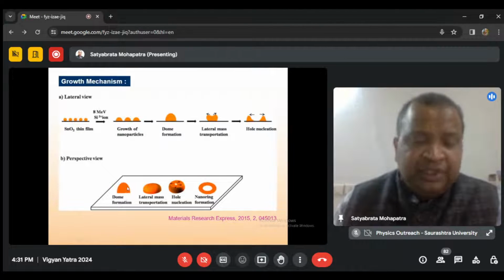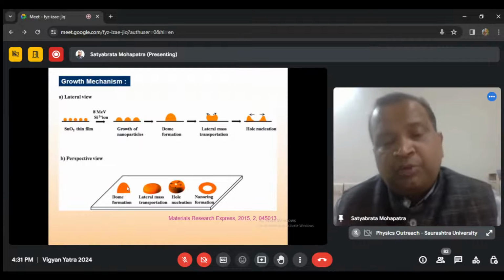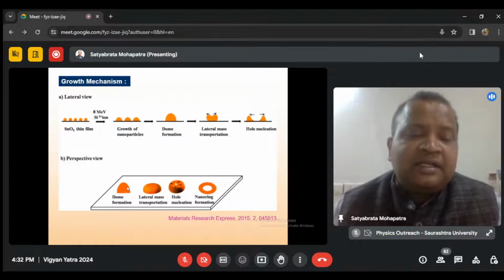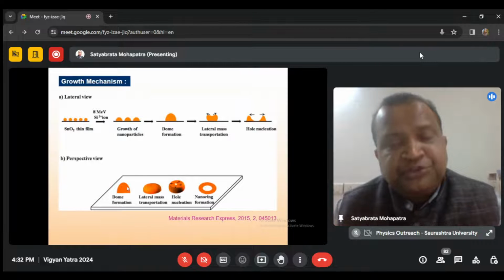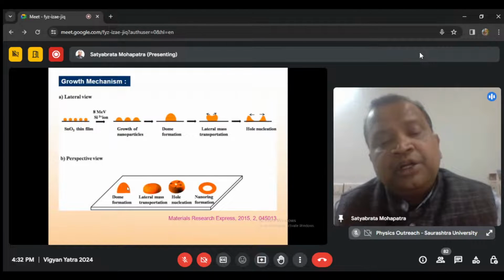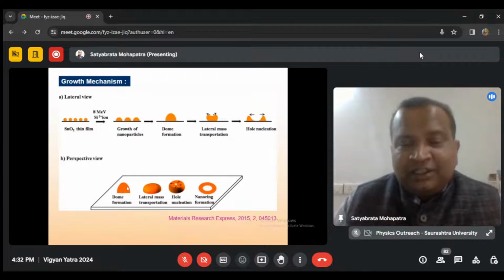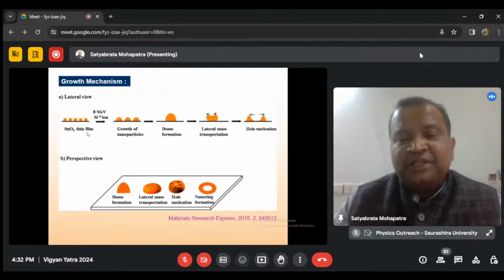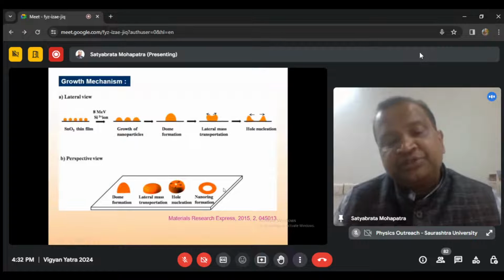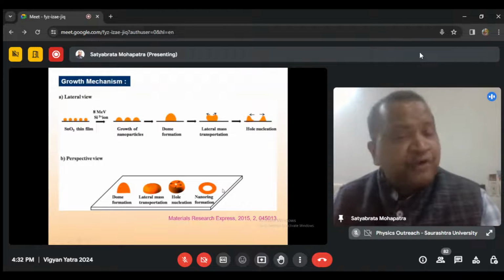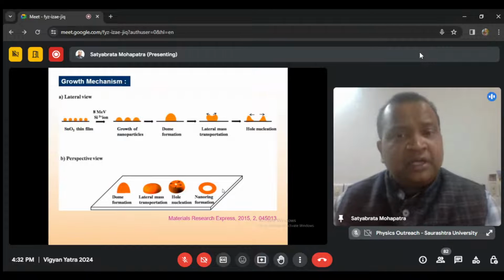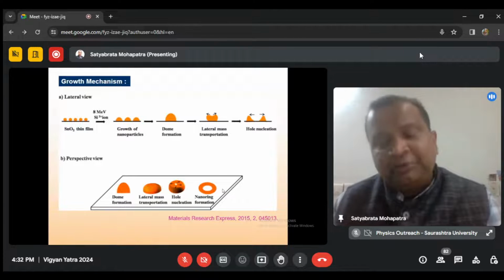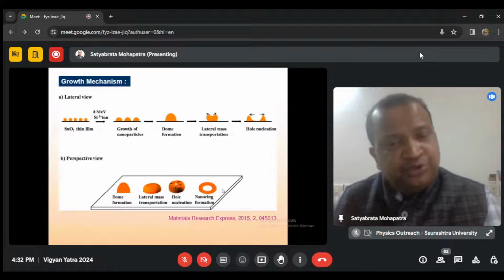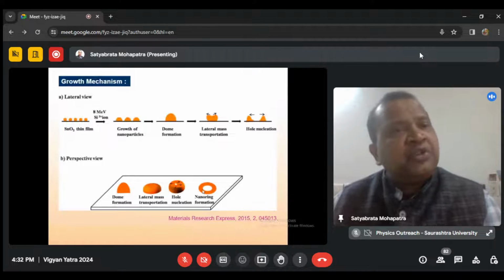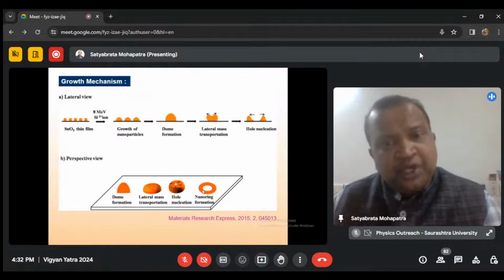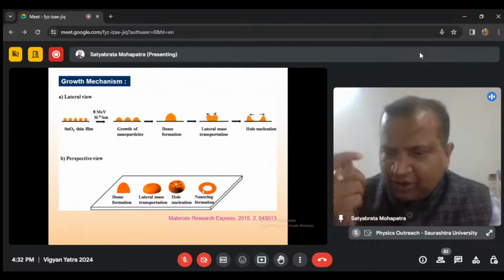Then as you keep increasing the fluence, there is stress that the film cannot handle, and there is lateral mass transportation in response to the deposition of huge energy, leading to the nucleation of holes. And this hole then increases in size, producing something like a nano ring. So this is the nano ring formation process in tin oxide. We have explored this for other metal oxide systems, and under some optimal conditions we can tune and produce nano rings and explore their gas sensing response. Here I am discussing tin oxide as a case study.